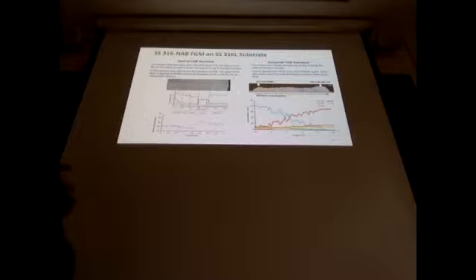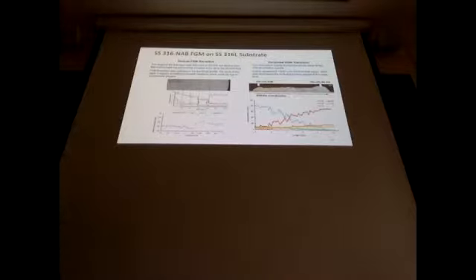One, we did a vertical, so we built a very simple wall. And the other, we did a horizontal transition. The idea is that we can start looking at how we did the vertical, understand what happens to the chemistry, and see if we can get that to correlate to the model that we built. This one was built vertically, a simple wall, and this one is built like a cladding layer right on top of the stainless steel. So we started with NAB and moved back to the stainless steel.